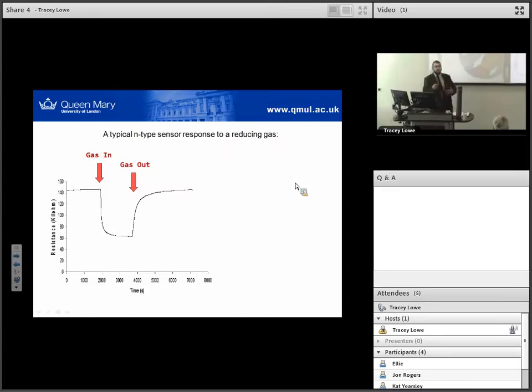So any kind of combustion reaction you may detect. A typical trace for an N-type material then is: you're in an oxygen atmosphere, you put your analyte gas in, you'll see some reaction which is releasing those electrons which have ionized your oxygen species. They'll go back into conduction band, resistance will lower, and then when your analyte gas is removed from the gas stream, you'll tend to go back towards your baseline amount.